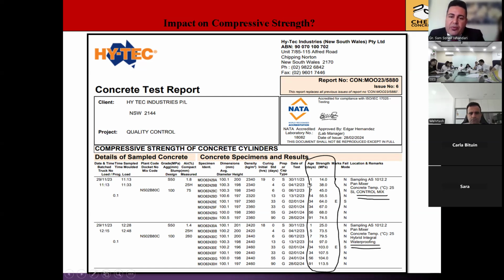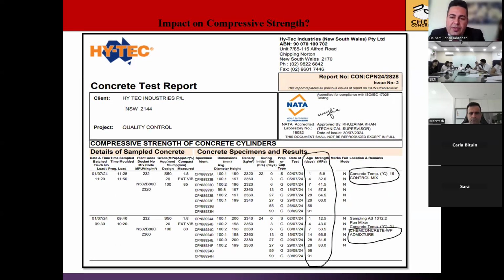compressive strength. For example, 1 day compressive strength was 14 MPa for control, 25 MPa for concrete treated with our admixture. 7 day compressive strength for control was 45 MPa. For our admixture, it was almost 80 MPa. So yes, similar results have been achieved at other curing days. You can see a huge improvement in the compressive strength test results.